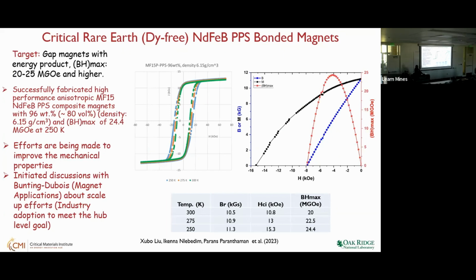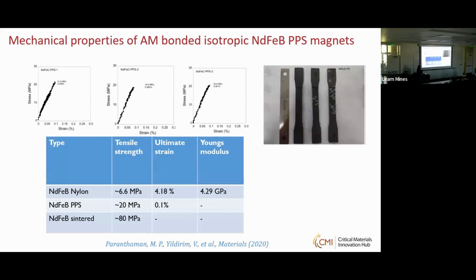And you can see when you heat it to higher temperature, it may lose all those alpha, beta we talked about. And if you look at the mechanical properties, still it's weak, I would say. Like nylon, you are 6.6 MPa, the tensile strength. PPS, you can go to 20 MPa. Sintered neodymium iron boron is 80 MPa. But you can add some additives, where we have looked at the carbon fiber addition. You can improve the strength. These are things you have to improve on some of the printed magnets.